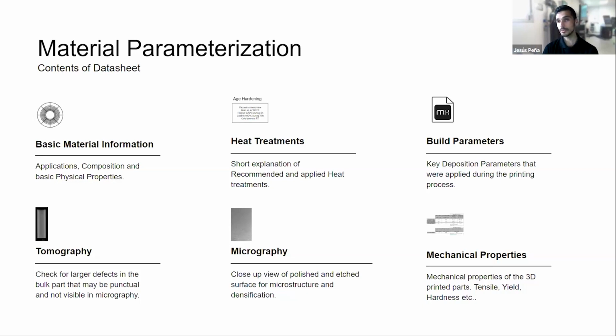And first of all, we need to make some iterations with the material. So we are selecting different velocities, different feed speeds, different laser powers, just to know what is the best configuration for my tomography test. In my tomography test, what I check is what we commented before: what energy density should I apply to my material to have fully dense parts? As soon as I have my parameters, I'm able to go with any kind of micrography or heat treatment recommendations, because I will have, let's say, insights into the mechanical properties and the properties of the materials overall I will have after printing.